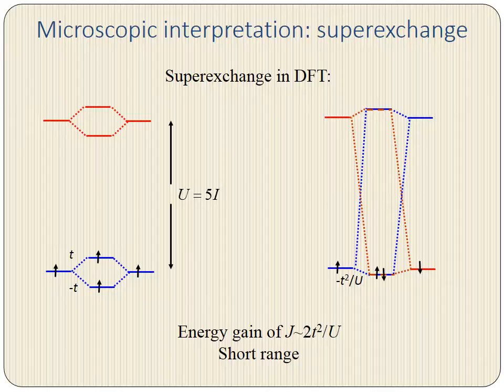So here we're going to review superexchange in the context of density functional theory. The basic picture is that you have two neighboring manganese ions, and that there is an effective amplitude for a d electron to hop from one manganese to another, which we parameterize by the value T. Note that here, effective hopping refers to the electron going over an intermediary atom, such as arsenic in our particular system. There is a Hubbard splitting between spin up and spin down, and it is given by the value U, which in DFT is equal to 5 times I, where I is the Hund's rule coupling.